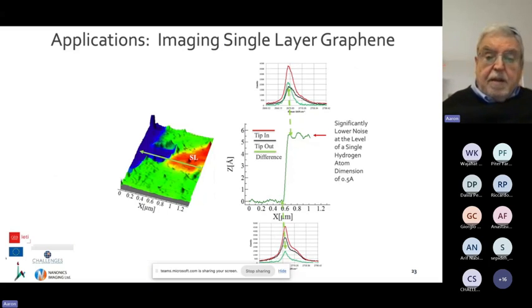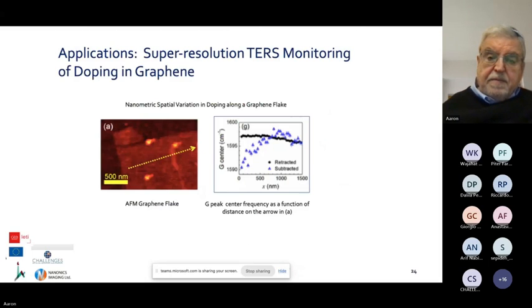So an application, for example, is getting high resolution single layer graphene. And you can see this is in contact, this is out of contact, this is difference. And you can go from a single layer to a multi-layer. That's this line over here. And it works very well for graphene. You can also, depending on the G band of graphene, actually follow the doping with about 50 nanometer resolution. That means the G band changes. In the far field, you don't see anything. Only with the plasmonic probe can you see those dots.